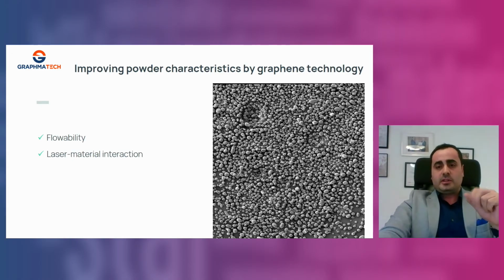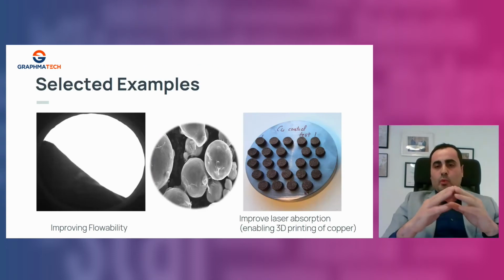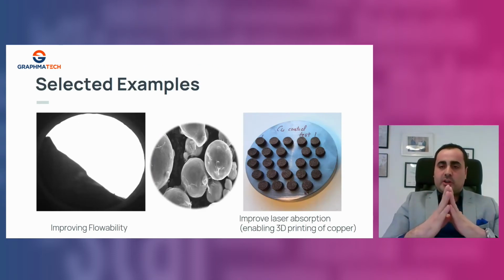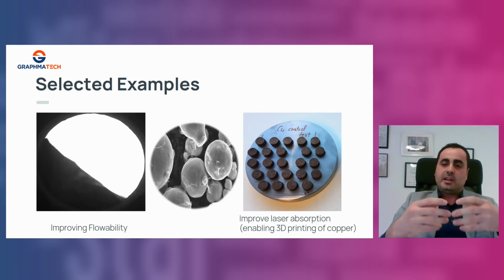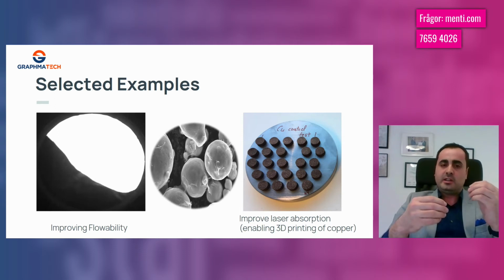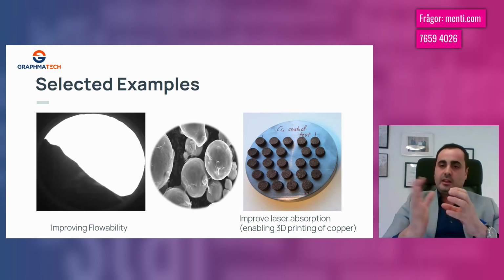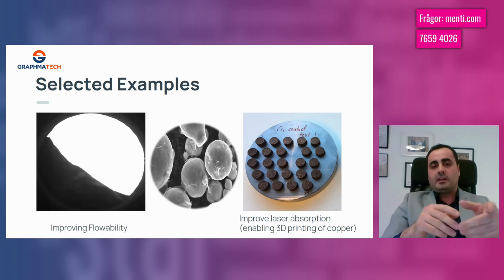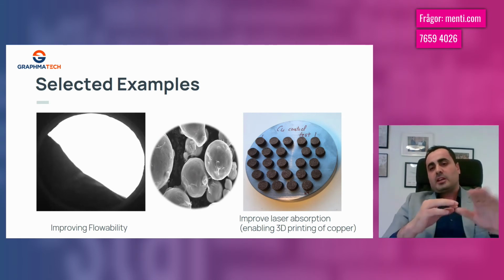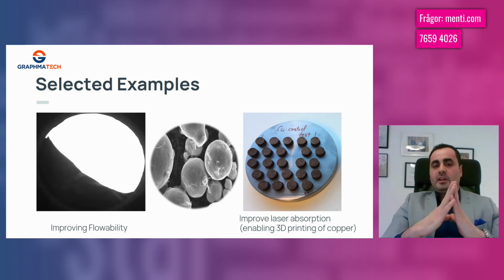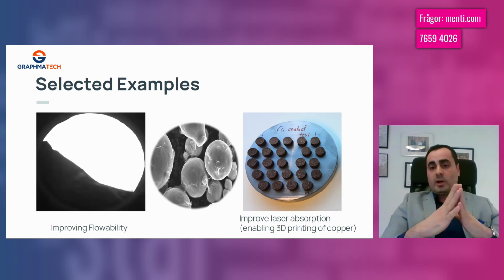So let's talk about the flowability and the laser material interaction as two examples of improving the powder characteristics. While putting graphene on the surface of the particles, we have the possibility to dramatically improve the flowability. When you have too fine metal powder, they have a problem that they stick together and they don't flow. But if you have graphene acting as a lubricant, then the problem is solved. And here I will show you, like you see the video here. This is a coated metal powder with graphene where the flowability has improved up to 61%.